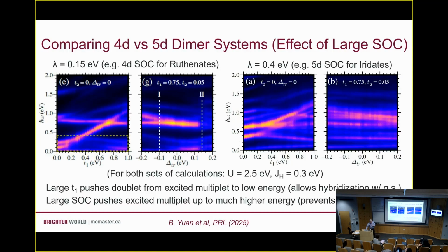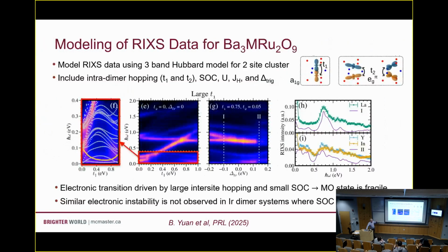I don't have a great answer for you there, other than the sense that you're shifting around this low energy spectral weight, so you're changing the shape of these d orbitals. Initially, people had tried to attribute this to a system where you had full molecular orbitals and half molecular orbitals forming. The idea was that in the lanthanum case you had molecular orbitals going along both directions, and in the other case only along one direction. That's not consistent with this. This is telling us that we're always in this molecular orbital regime, but that you're changing the position of these molecular orbitals as you tune the trigonal crystal field. It's not telling you about nematic order. Sure, I see.